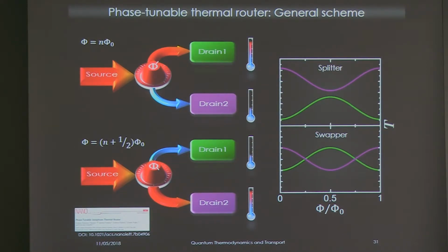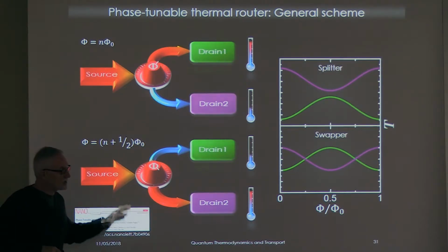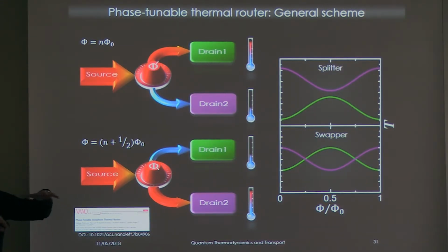So in this way, by modulating the flux, we can make the temperature of one to increase and the other to diminish. So you see that the temperature of the object, if the core of the device is a SQUID, will behave in anti-phase, one with respect to the other. And what is interesting, the system can be used as a splitter because we can divide the two heat fluxes according to construction parameters. And the general modulation will be given by the quantum phase mechanism existing in the system. And then there is another possibility to make swapping of the temperature. What is swapping? If we construct the system well, we can make the temperature of one become larger than the other, at will.